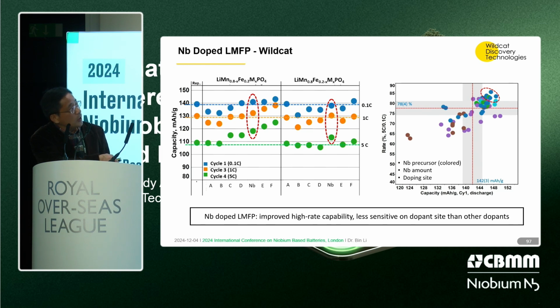Here you can see the blue color showing the best in terms of cycle 1 capacity and also 5C rate capability. For example, if I use 3 to 5 different precursors, and 3 to 5 different amounts, and then 3 to 5 different synthesis conditions, the combination number is quite huge. With the traditional way, you just cannot do it. But with our high throughput, we can do that.